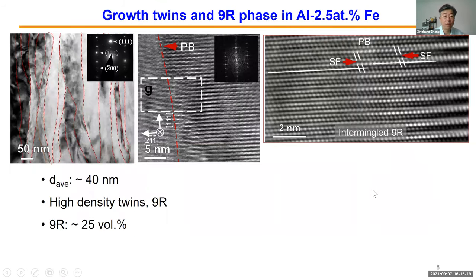And when we look at this under higher resolution, looking for the defects, this is again a cross-sectional view of this aluminum. The red dotted line shows the grain boundaries. Grain size is about 40 nanometers. If you look at high resolution, zooming into some of these boundaries, you find a huge amount of stacking faults, and pretty broad stacking faults. In many cases, the entire column can be filled with this kind of stacking fault.